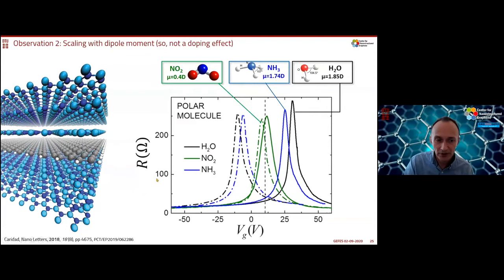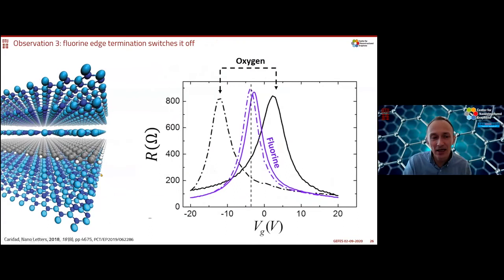Well, that is something Mads, our dear chairman, and also José looked a lot into. And actually, when you change the edge termination, which we're able to controllably do in our clean room processes, we can replace the oxygen with fluorine on the same structure. We see that with oxygen, we have this hysteretic shift, and with fluorine, it's nearly gone.